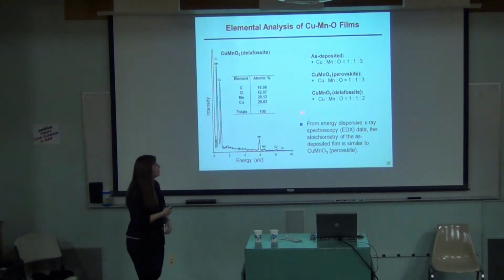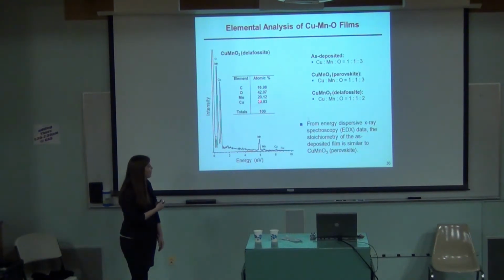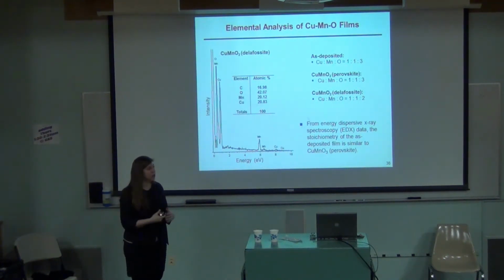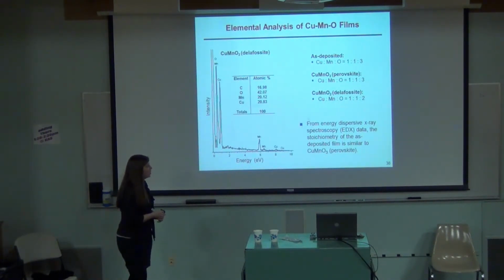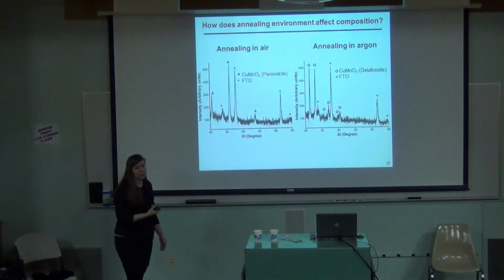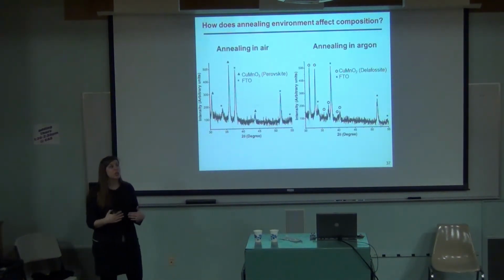And this is just to show you some EDX spectrum. This gives you your composition. This proves that we did have a 1:1:3 ratio, meaning that it was more like the perovskite structure, and then when we annealed we got the perovskite and the Delafossite. So that was just to show us that, because XRD can only see crystalline materials, so we had to use EDX to show us our ratios of copper and manganese to oxygen, because that can look at non-crystalline materials, so you can just get elemental ratios with that.